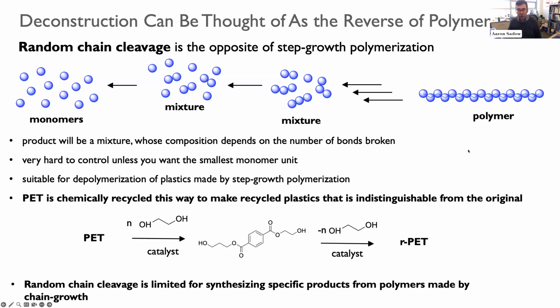So if we took this polymer and started breaking chains randomly, then that's the opposite of a step growth polymerization. And the mixture that you get out in this conversion, until you get to a monomer, is going to be a mixture of short chains, medium chains, long chains that are just governed by the statistics of random cleavage. And the control you can get is at the end of the reaction, if you're making monomers, you could make 100% monomers. So that's great.